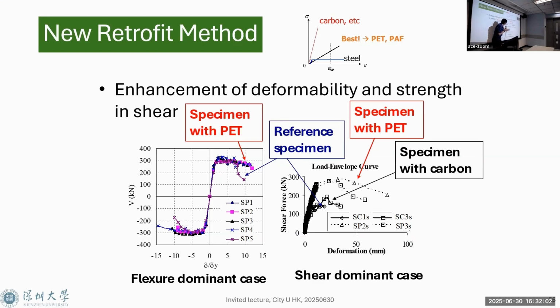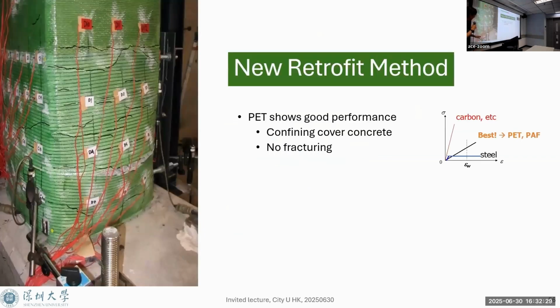And the specimen with a PET fiber is like this, and the carbon is like this, and the reference specimen is like this. So if your shear reinforcement doesn't show breakage, this is perfect. But you better still have rather high stiffness. With steel reinforcement, no breakage, but yielding, so the stiffness must become much less. So this shows some experimental results.